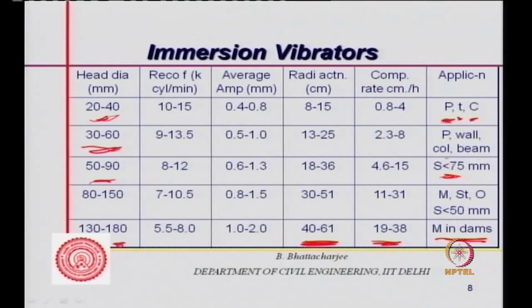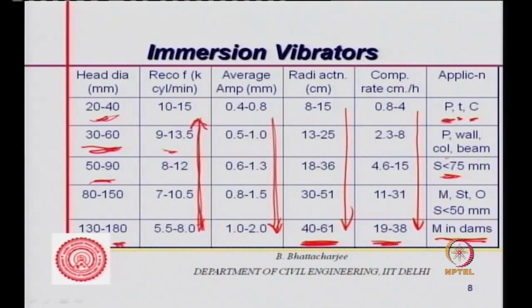So plastic concrete, wall, column, beam, you can use 30 to 60, and this range, as you see, it reduces here 10 to 15, 9 to 13.5, and so on. And average amplitude increases along this direction. This becomes lower, this increases along this direction. Radius of action increases along this direction, and compaction rate also increases along this direction. So 80 to 150 you will be using actually mass concrete.